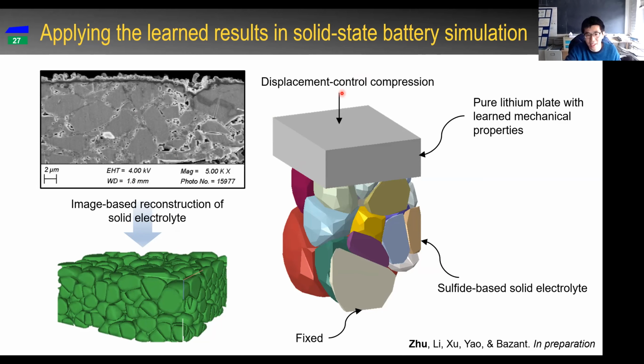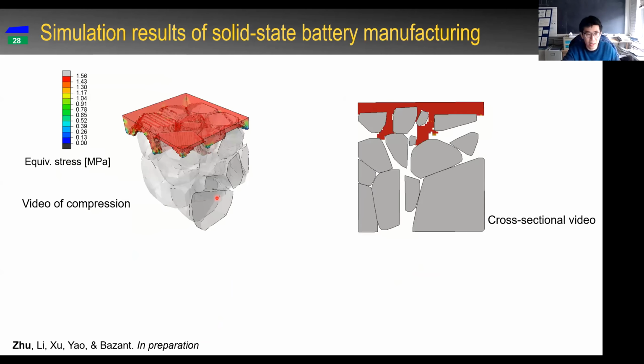We apply it here to mimic the real-world manufacturing procedure. There is usually a displacement-control compression, and we do this simulation. This is fixed, and this is displacement control. The solid electrolyte is a sulfide-based solid electrolyte, and it is elastic-plastic, and all the particles can move. Here are the simulation results. There are two videos here.